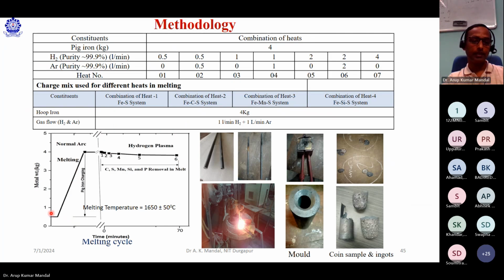You can see here, up to the melting experiment, we use the normal arc, because a hollow electrode during the conventional melting may jam the holes. Therefore, after melting, when liquid metal is prepared, then we transfer it to the hydrogen plasma by replacing the solid electrode with a hollow electrode. Then we have taken some coin samples. You can see coin samples by taking this crucible copper mold, and we analyze it.